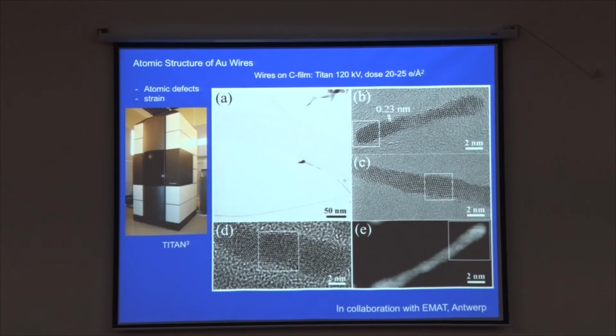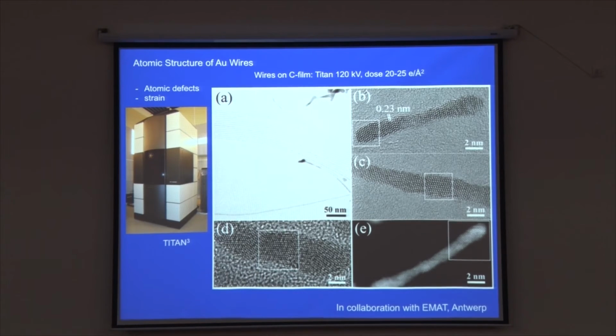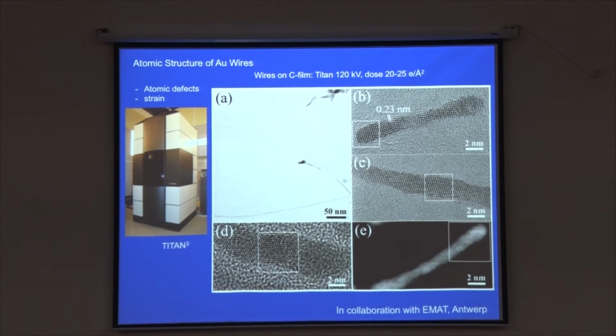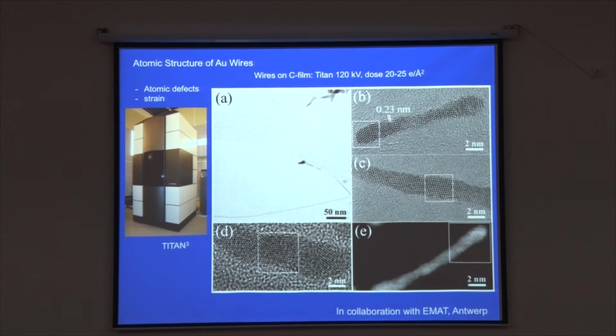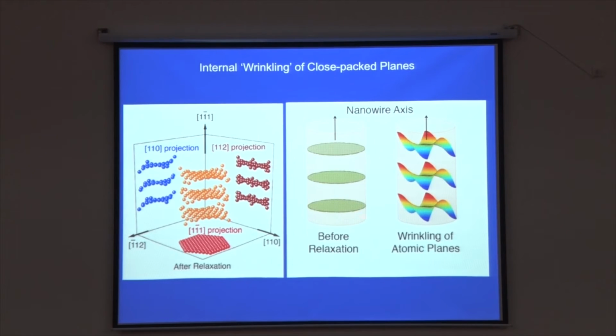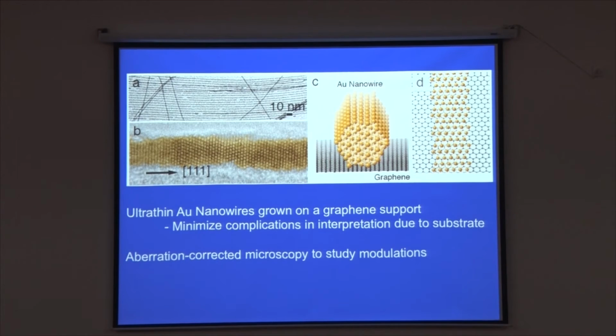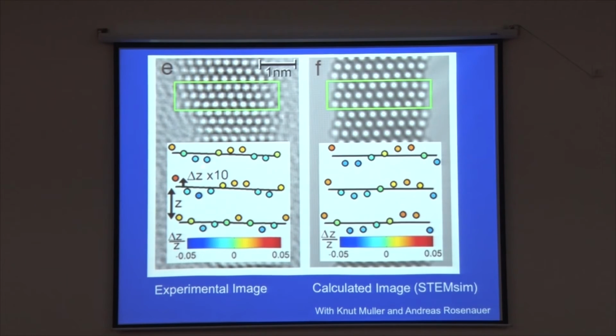The good thing about the modern-day electron microscope is that we can look at individual atomic columns and look at how they displace from their actual positions. This is the kind of displacement that we are talking about. These are of the order of a few tens of picometers. What we have been able to do is minimize effects from the substrate on the positions of the atoms. We have put it on a very well-defined substrate, so that we can subtract out the contribution by some kind of Fourier filtering. That's basically a graphene substrate. We drop these wires or grow these wires on graphene and look at them in the electron microscope. And we do find that we can see the kinds of displacements that are predicted by theory in these wires.